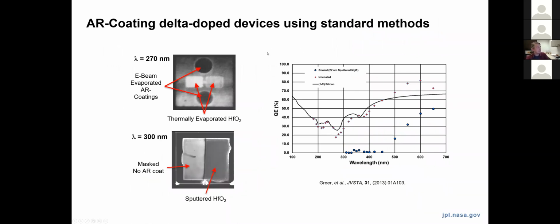I'll talk about atomic layer deposition in a few slides, but what led us in that direction was some early work that looked at different optical thin film coating processes to deposit these anti-reflection coatings. We looked at E-beam evaporation and sputtering for some of these films. The images on the left here are showing flat field images at monochromatic illumination for devices that had different coatings on different parts of the detector.